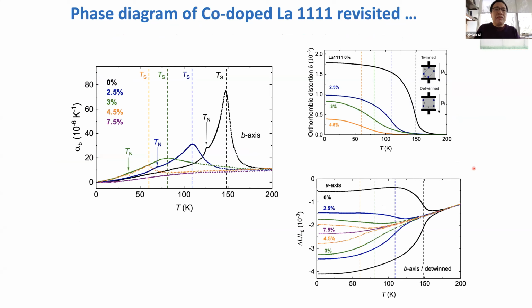And then we measured the phase diagram, and we did a broad spectrum of techniques to study that. And this is, let's say, a highest resolution measurement of the structure. So the dilatometry, where you see the temperature derivative of the lattice constants, you see the structural phase transition or the nematic phase transition here, and then you see the magnetic phase transition, even there, even in the lattice constant. You can see that as a function of doping, the transition shifts to lower temperatures, as we know, and everything becomes very broad. So in particular, this structural phase transition becomes very broad if you start to dope it. And you can also see that from the lattice constants, which you can derive from such kind of measurements by measuring twinned and detwinned directions. And then you see this sharp transition becomes broader and shifts to lower temperatures before it disappears.